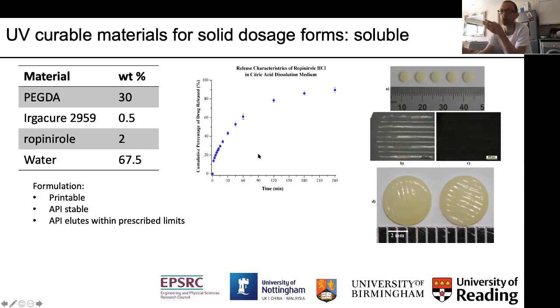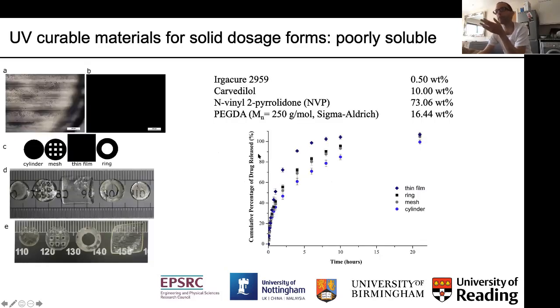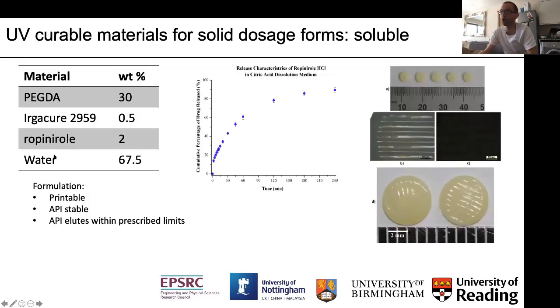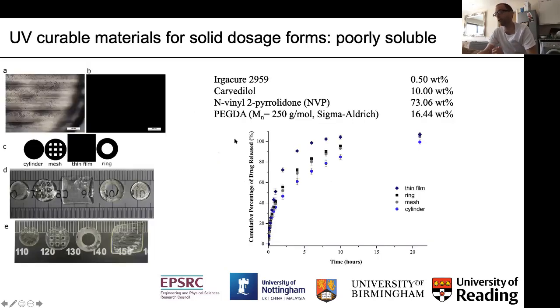So when we came to then thinking about poorly soluble APIs, we then have a pretty difficult problem because we then have a lot of water in there. The water's been used to dissolve the soluble API. When we've got a poorly soluble API, that's not going to go in at all. We're going to have a bit of a problem. So we decided to try and keep the core of the UV curable element of our formulation, the polyethylene glycol diacrylate, the Irgacure, which is the photoinitiator, and then we've got the carvedilol in there, which is poorly soluble. But instead of the water, we chose to go to a different kind of solvent. So we swapped out the solvent.